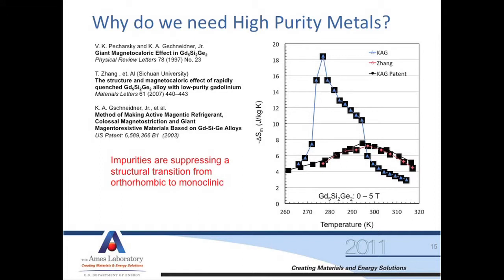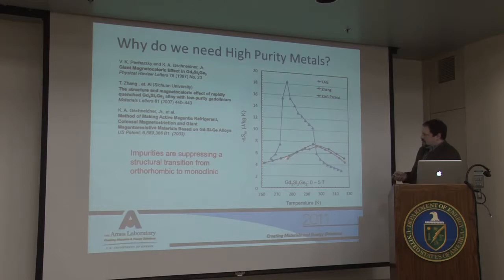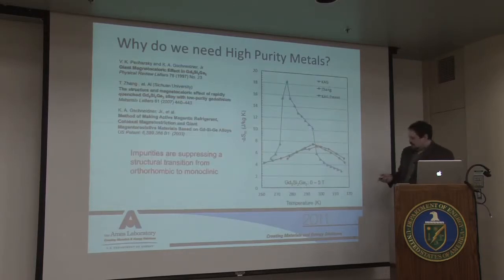Here's an example of work we've done on how the purity of materials affects the properties. This blue chart here is the entropy change — and you can do a calculation to make that a temperature change — of gadolinium silicon germanium, made from very high purity materials. They have used it as a prototype for magnetic refrigeration purposes. But if you take a lower quality gadolinium and silicon, this is the entropy change. You're not going to get a lot of temperature change with that little available entropy.